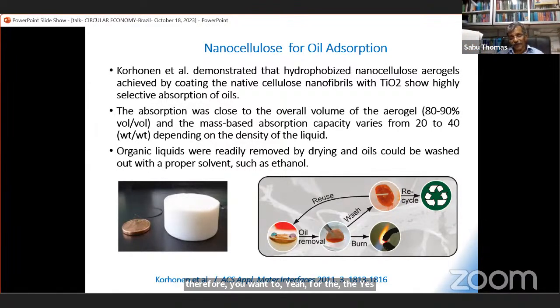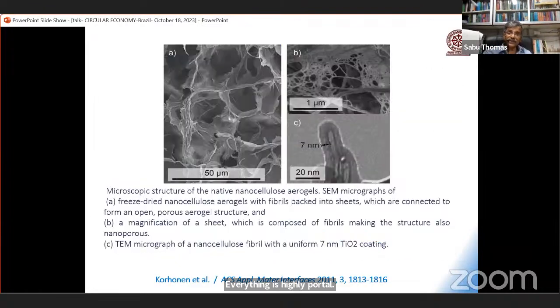So what the Finland group did is something very interesting. Dear colleagues, dear students, please look at this. The Finland group made nanocellulose. How do you make it? You have 1 or 2% of nanocellulose in water. Through a freeze-drying process, you can make a beautiful aerogel, which is highly porous. And then they did something interesting. They made a coating of nanocellulose with titanium dioxide. You see, they made a coating. These dry nanocellulose aerogels were coated with it.